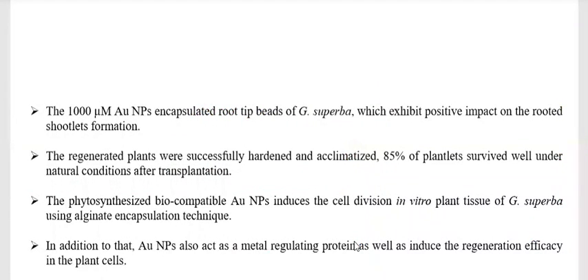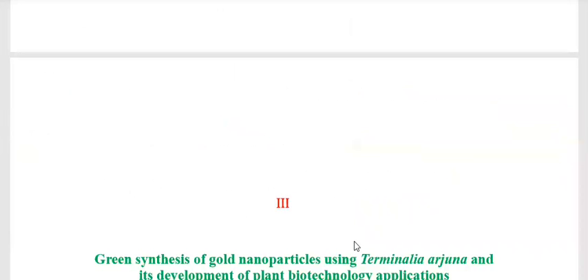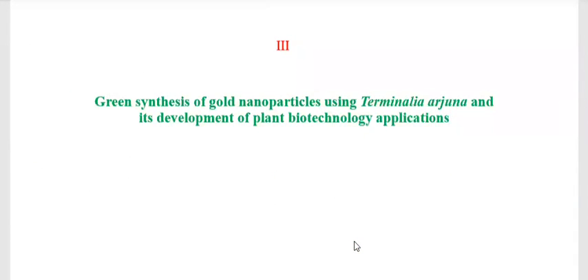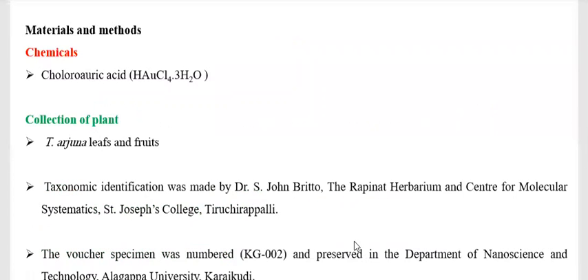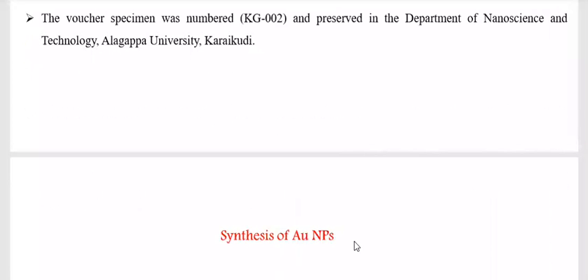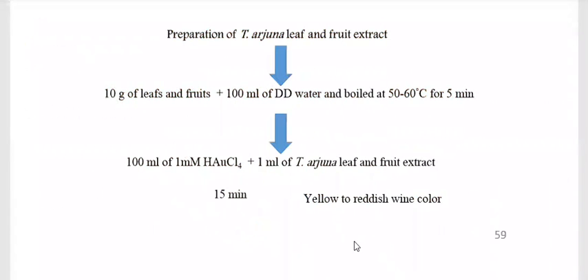The second one is the same procedure. We can use Terminalia arjuna leaf and fruit extract, and parallelly investigate 10 gram of leaf extract and fruit extract in double distilled water boiled at 50 to 60 degrees. In addition of gold chloride, you get the gold nanoparticles. We investigate the mitotic cell division of Allium cepa and pollen germination of Gloriosa superba. This is the UV analysis: 530 nanometer and 522 nanometer for leaf and fruits.